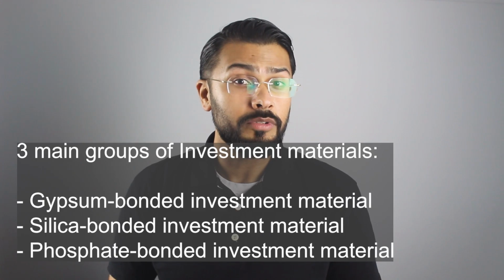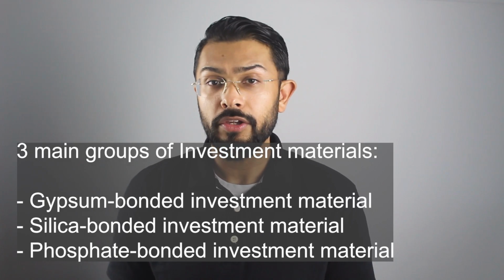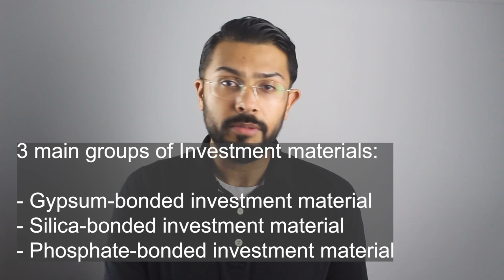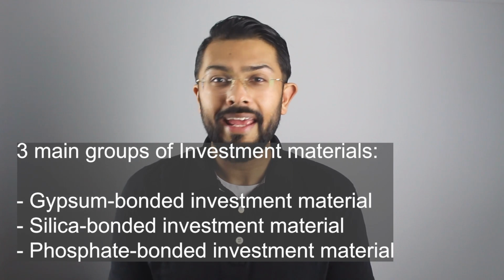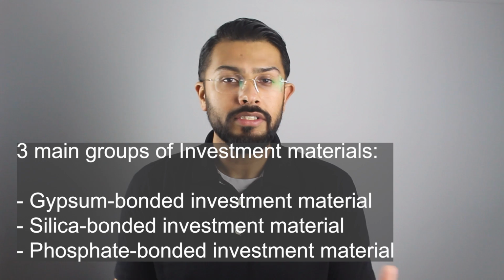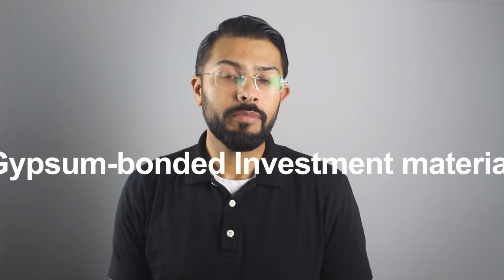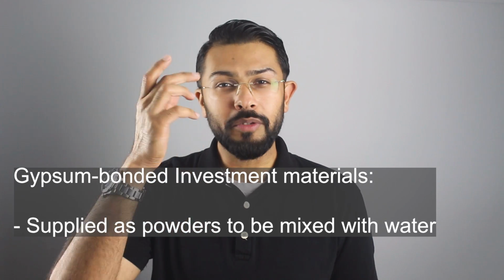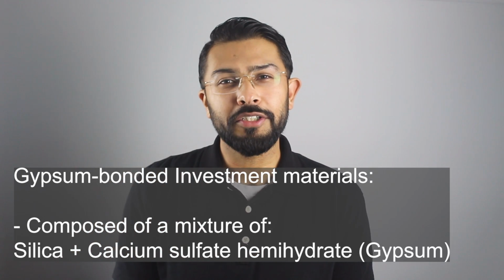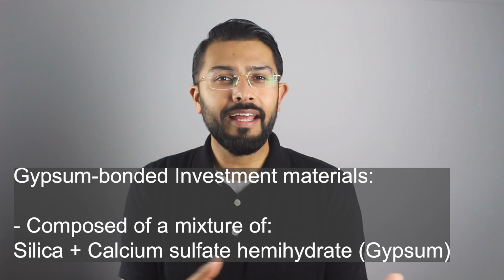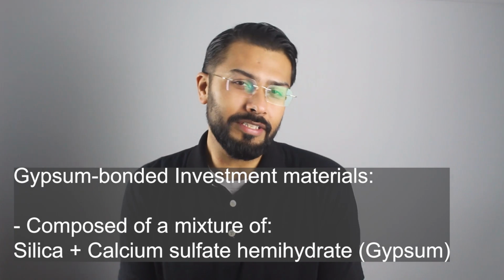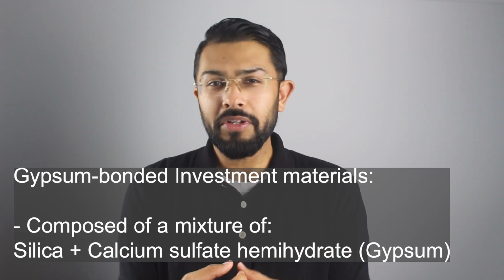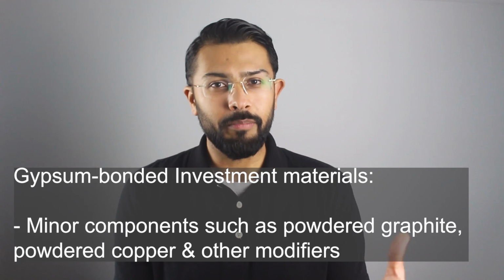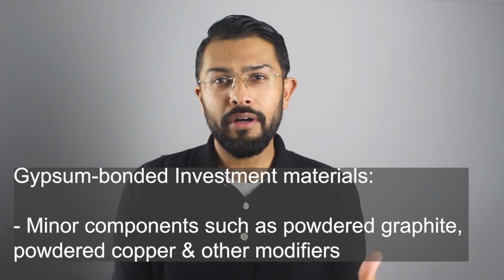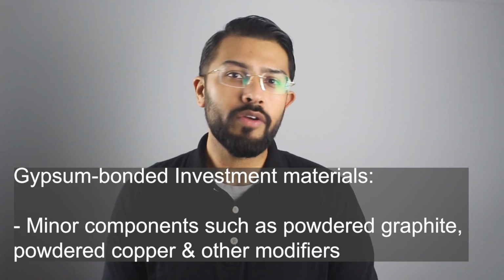There are three main groups of investment material that are commonly used. They are referred to as gypsum-bonded, silica-bonded, and phosphate-bonded. First, let's talk about gypsum-bonded materials. These materials are supplied as powders which are mixed with water and are composed of a mixture of silica and calcium sulfate hemihydrate, which is gypsum, together with minor components including powdered graphite or powdered copper and various modifiers